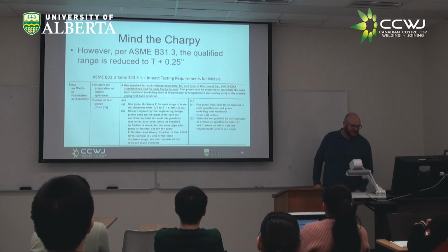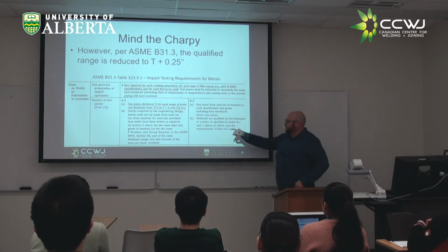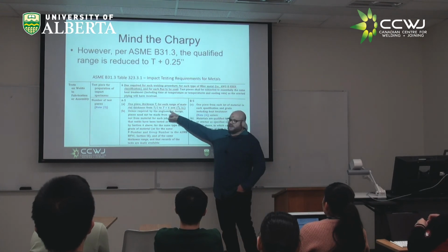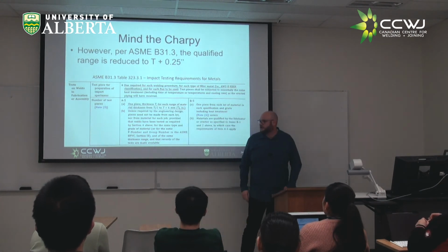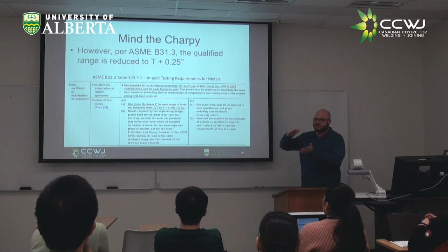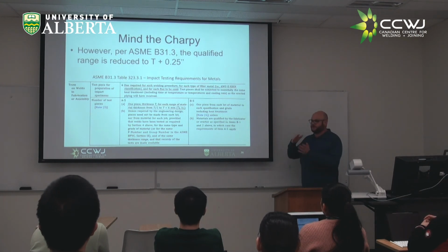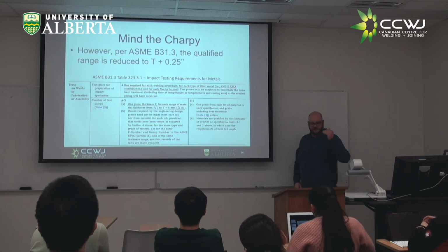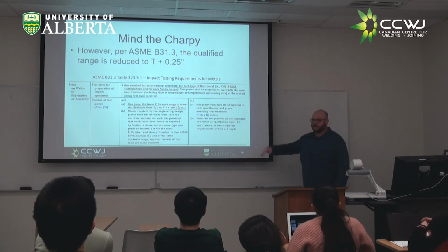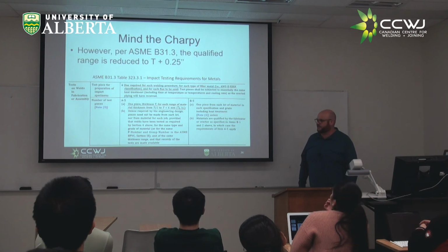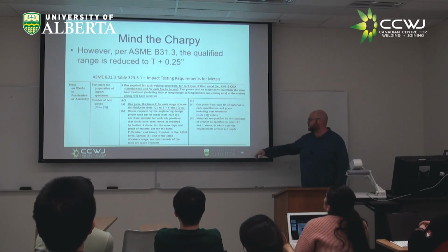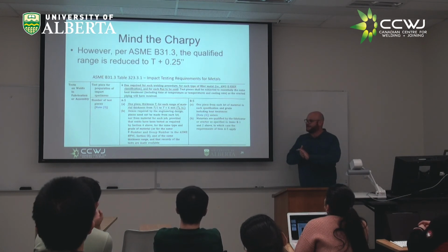And you also have to understand that no matter what you do, it's still limited not to 2T, but to T plus a quarter inch. So you can go through your draft procedure, and if you don't understand that it's going to be used in B31.3, you think you have it. You've done a coupon on a half inch, you're qualified up to 1 inch, and your application is for something about 800 thou, or just over 3/4 of an inch. You go to B31.3 and you can't use it. And this has happened more than once. Vendors get very angry because they say, well, it meets ASME 9.